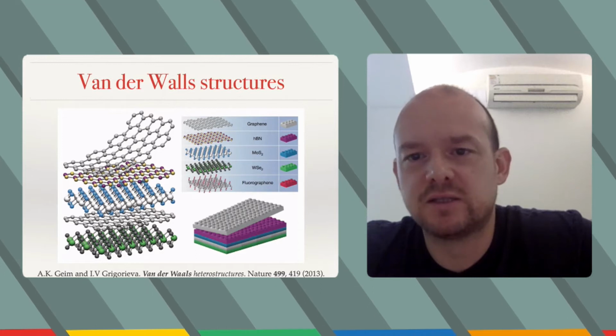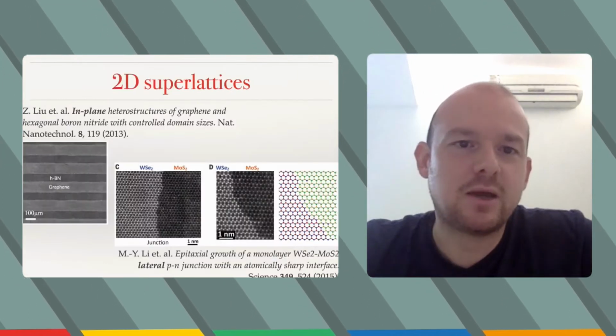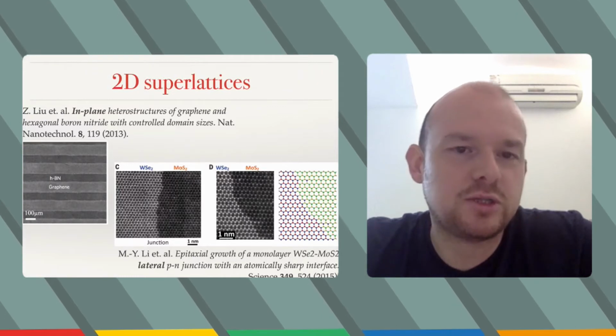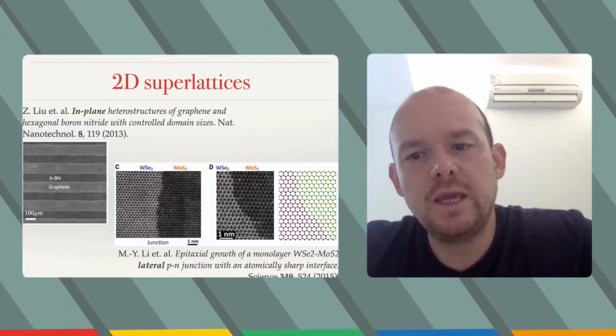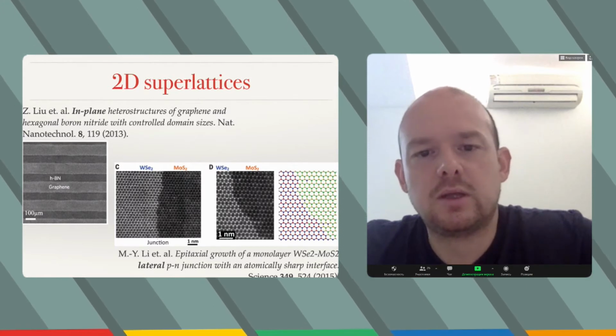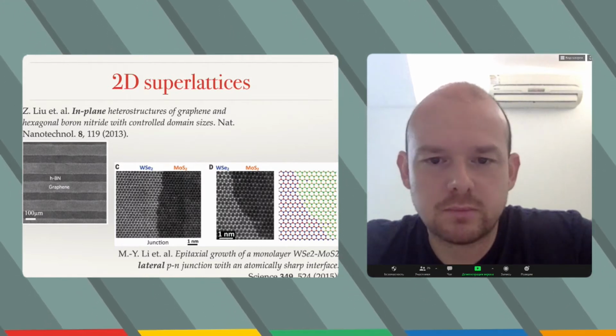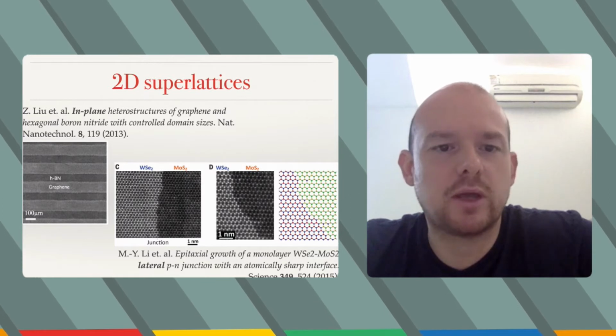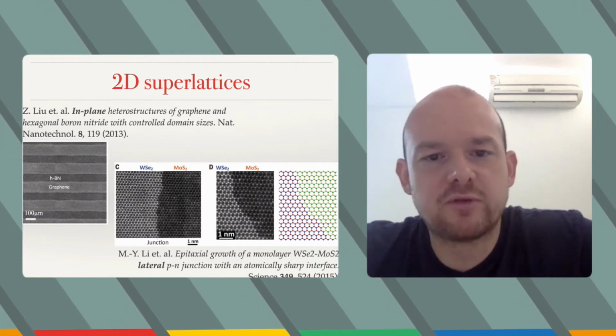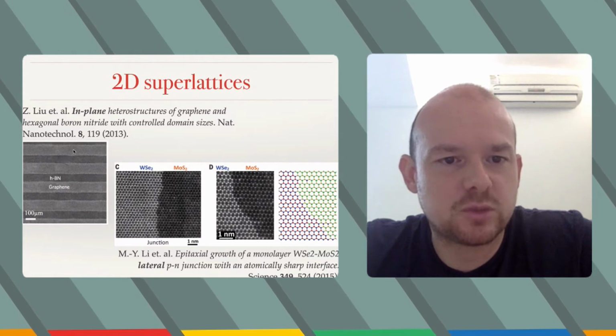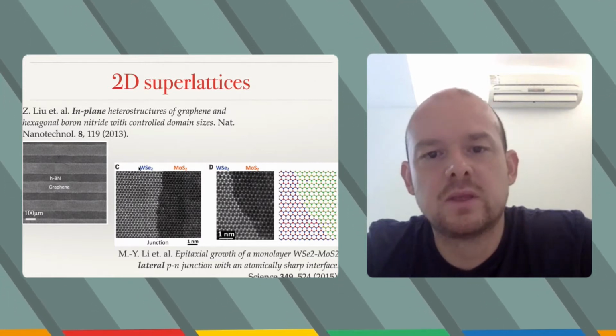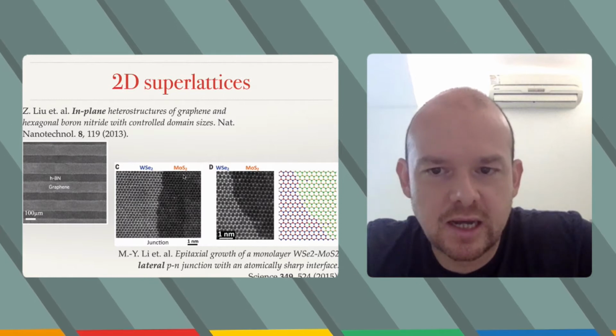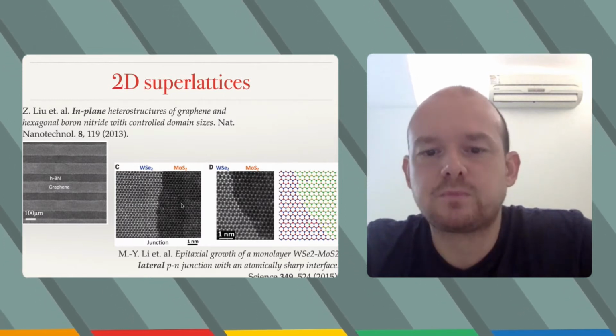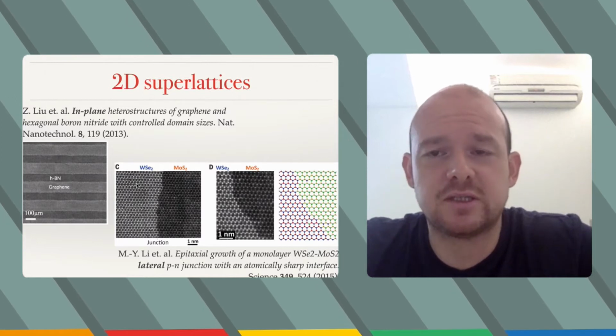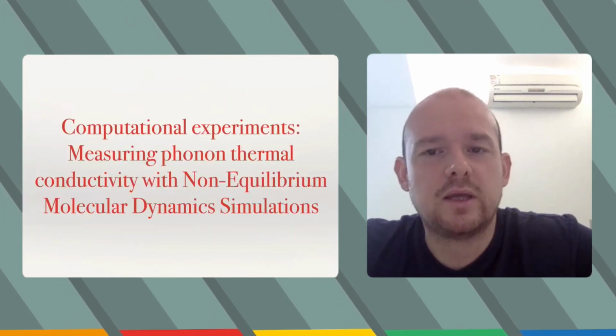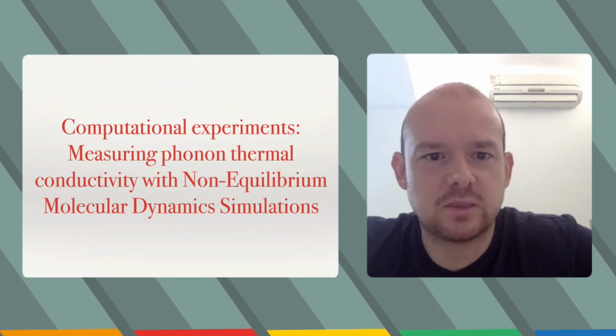So they can be combined in these so-called van der Waals structures, but they can also be combined in what we call 2D superlattices. So these are in-plane structures. This is still a planar, single-layer material, but they are composed of more than one material. So for example, here you have these superlattices of graphene and boron nitride. Here you have tungsten selenide and molybdenum disulfide. And all of these have been produced experimentally. These are not things that exist only in my computers, which leads me to my next important point.